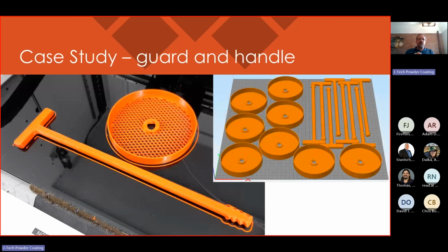But the print time for this for a pair was 1 hour and 24 minutes, and we expect that we would be able to get that down to about 1 hour per print. 8 of these fit on the bed so that multiple sets can be run at a time. It's really a great example of short run production.